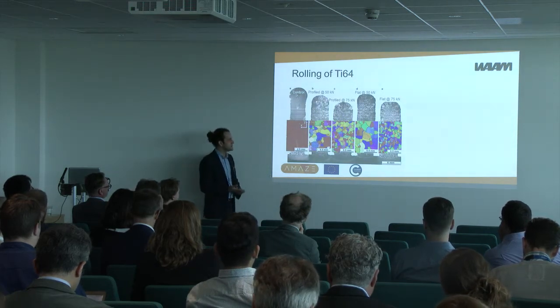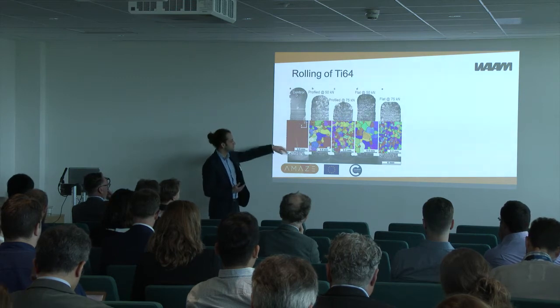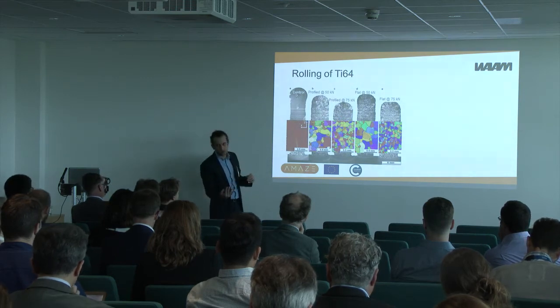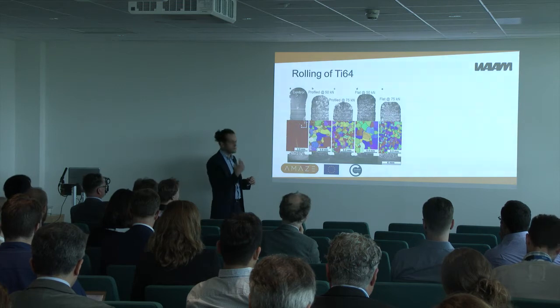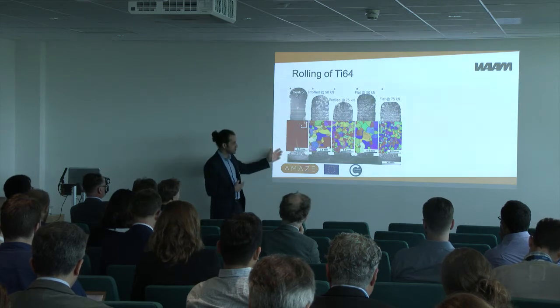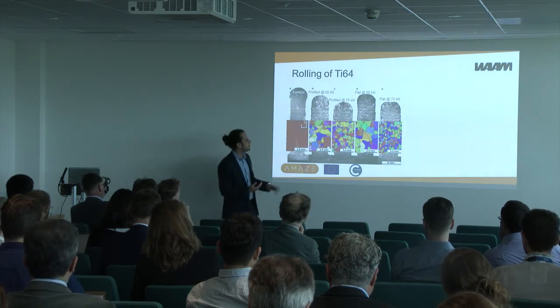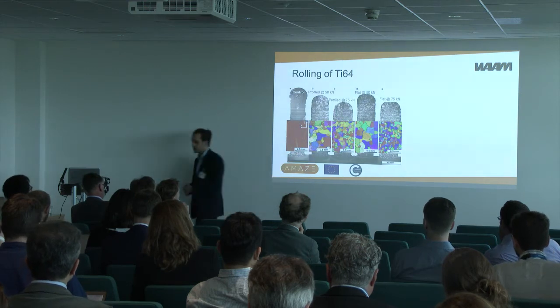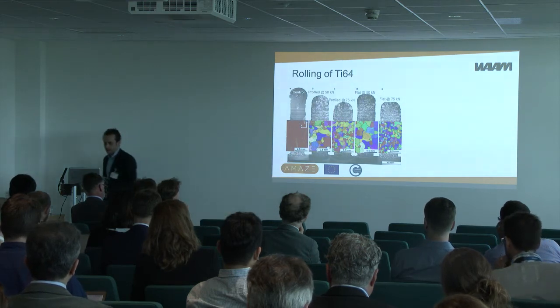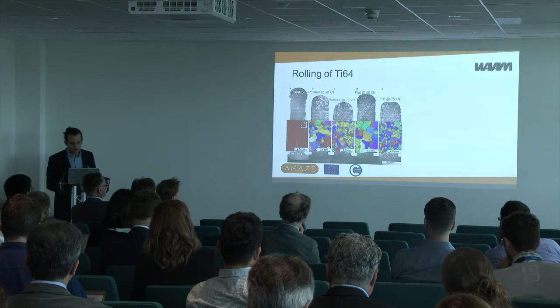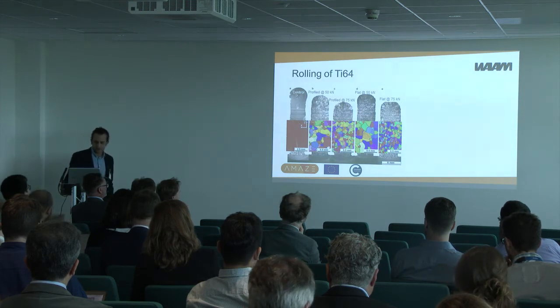But the other thing you need to see is that in this case, the color scheme suggests that the grains are growing all in the vertical direction in the 001, and that also gives anisotropy to the mechanical properties. While in this case, as you can see, the colors are much more random, and therefore we could argue that the texture is much less than the control case.